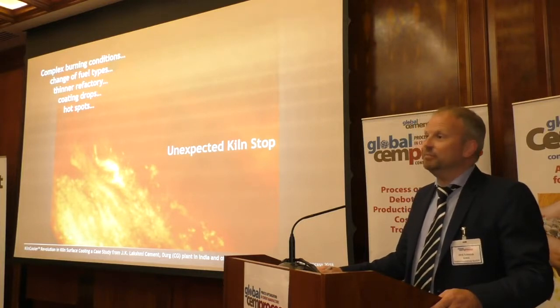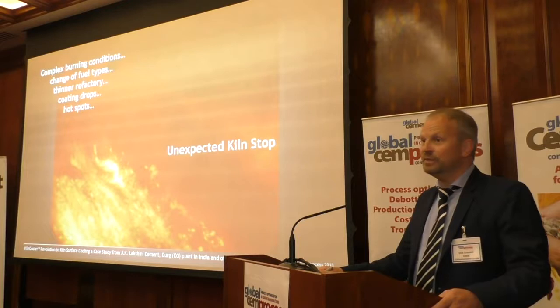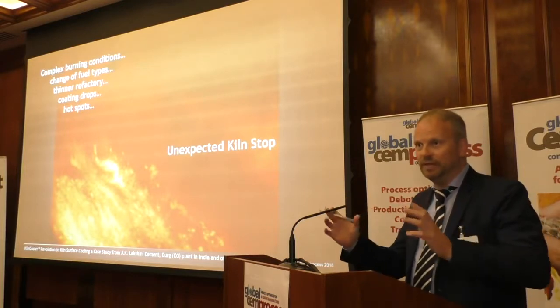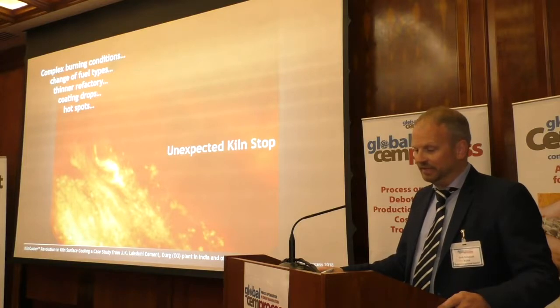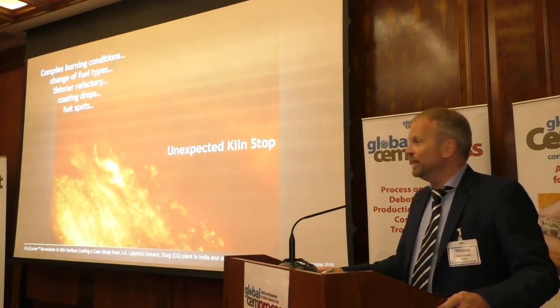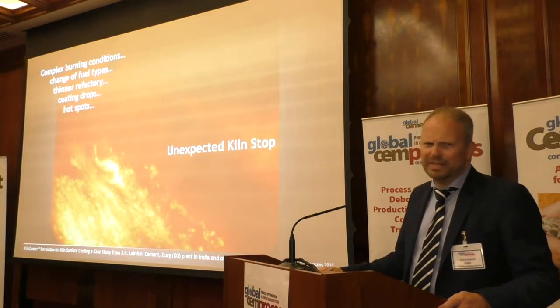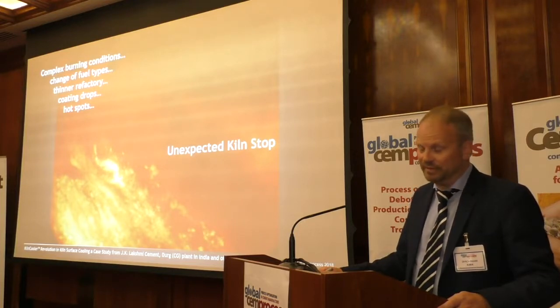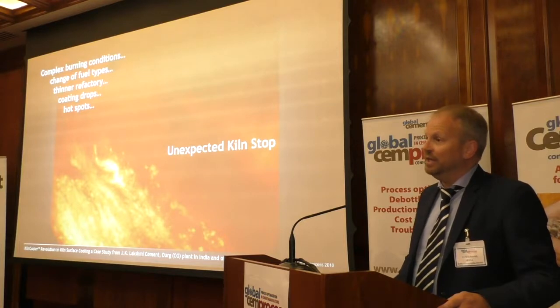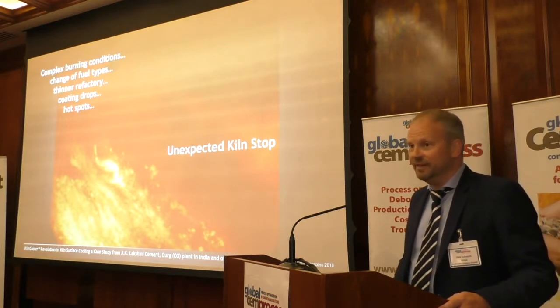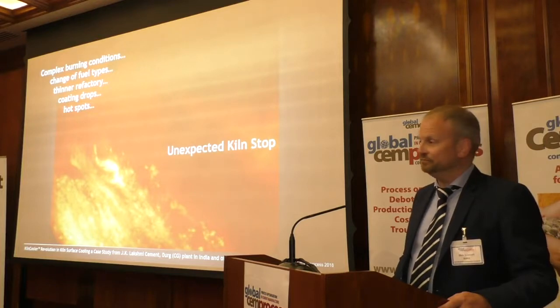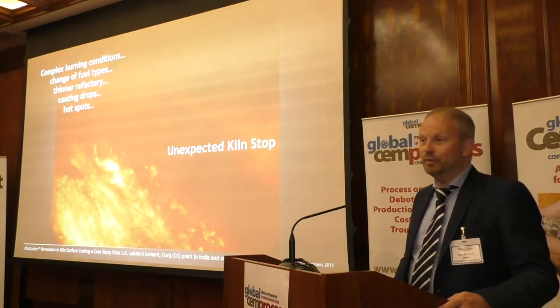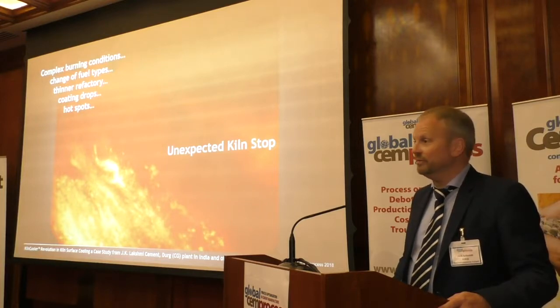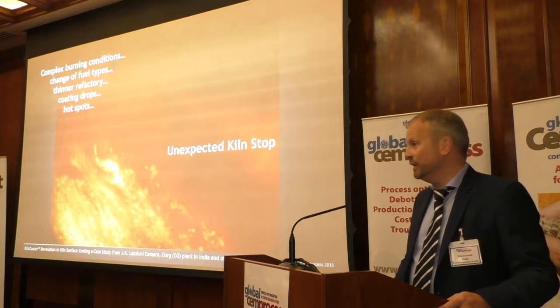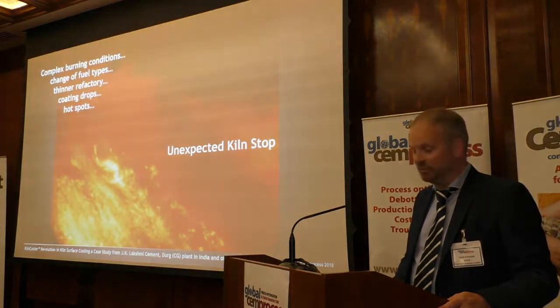Why? Because the flexibility of the kiln increases. You don't have this stability, this corset of bricks anymore in your kiln. And then, of course, with these coating drops you create hot spots, not even red spots. The hot spot comes before. And I speak about temperatures below 500 degrees, and I will explain you why. If it is above 500 degrees or even 470, it depends on the company, let me say, rules, you are fighting with an unexpected kiln stop. Because if a brick falls out, you are not able to operate your rotary kiln forward, you have to stop it to prevent it from damages.